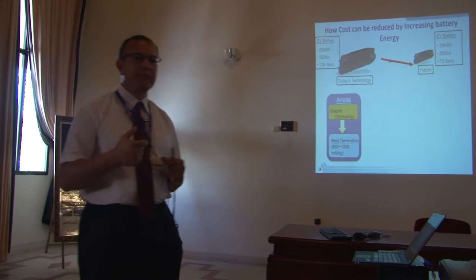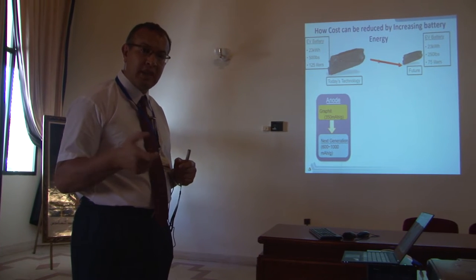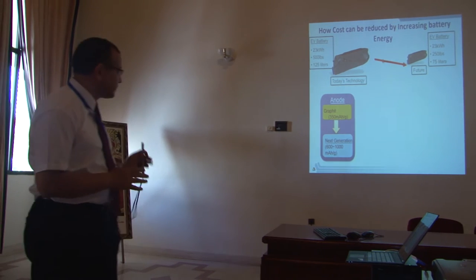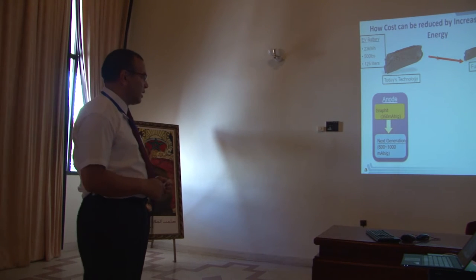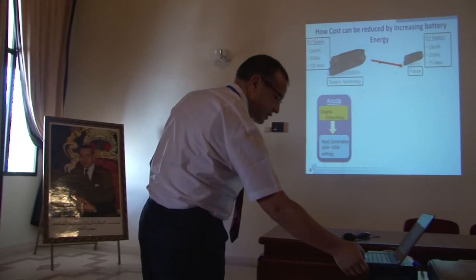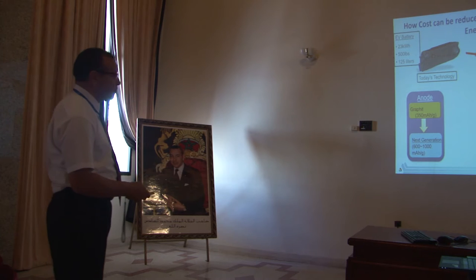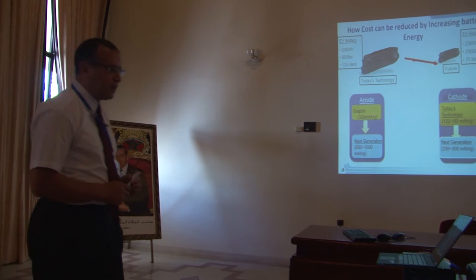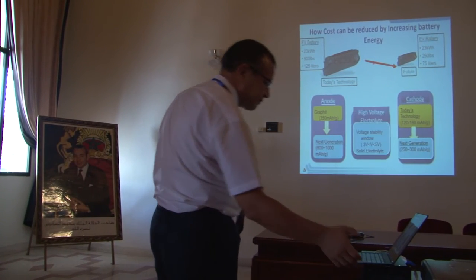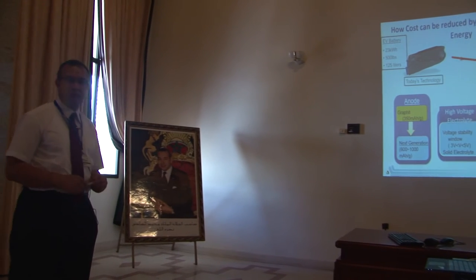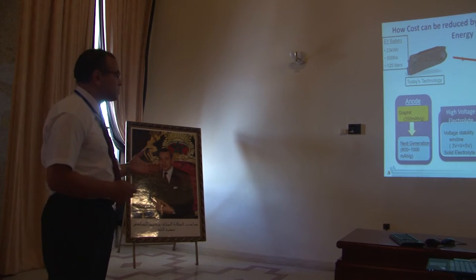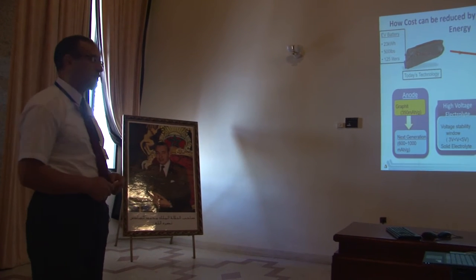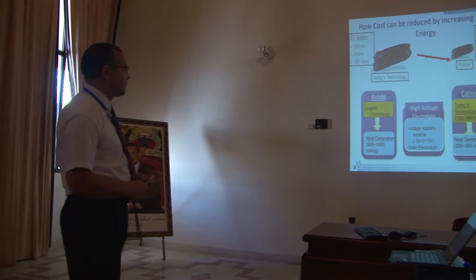The reason is there is no coating technology that can give you very thick electrodes at the speed of today. So if you can achieve 1,000, that's almost three times. And if you can develop a cathode material that has higher capacity than today's, our target is about 300 milliampere hours per gram, then by coupling these two systems, we can easily double the energy density of the lithium ion. You can also do that by increasing the voltage. As it stands, there are cathode materials like the NCA. When you go higher in voltage, you can get much higher capacity. You can get 250 or 260 milliampere hours per gram. The problem is they are very unstable. So these are the strategies.